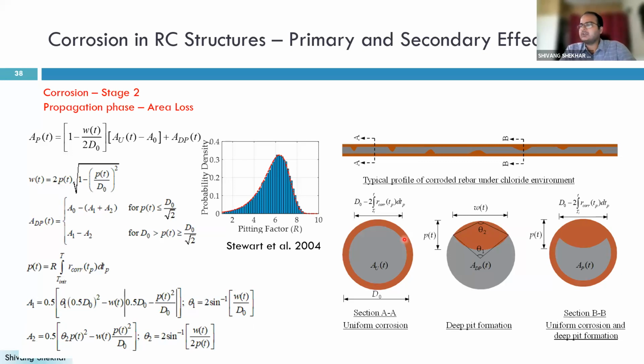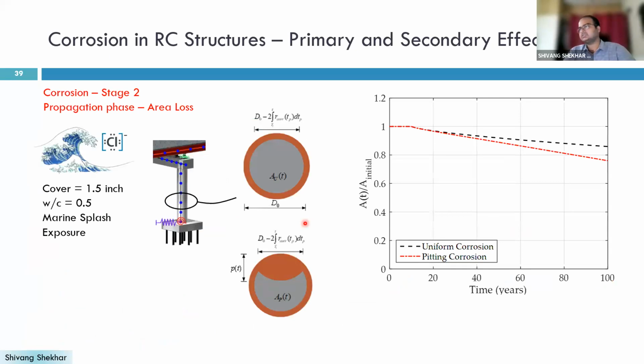accelerated corrosion test, and then measures the pitting factor at different locations across the length of the rebar. And then based on this, he suggested a distribution. Again, why a distribution? Because there is an uncertainty. So he suggested a distribution for the pitting factor. Specifically here, it is a Gumbel extreme value kind of distribution.